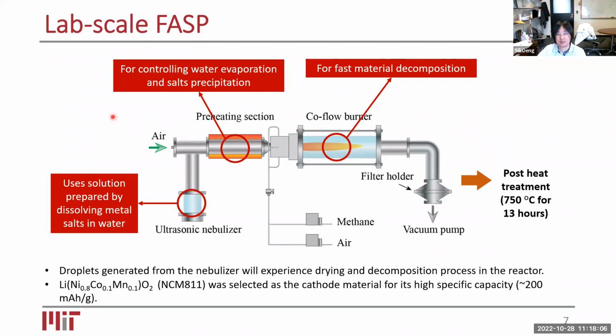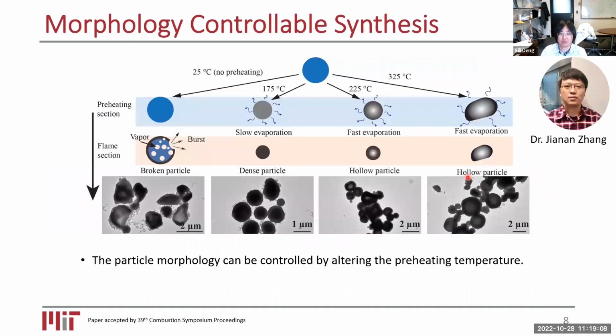So the practice right now here is to compare this precursor generation part with the co-precipitation method and demonstrate that this method indeed can result in the desired product. And as a case of demonstration, we picked NCM 811, where the N stands for nickel, and thermodynamically, this type of composition will give us a high theoretical capacity due to the high nickel composition. However, in industry, this has been very difficult to synthesize. Even in the literature, when people try to use the spray pyrolysis method for this high nickel component, it's quite difficult to do. And what I mean by really good performance is that if we can achieve a specific capacity of about 200 milliamp hour per gram, that is really a benchmark or milestone to achieve.